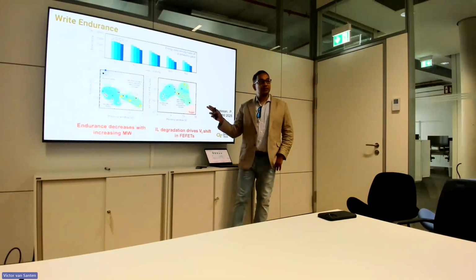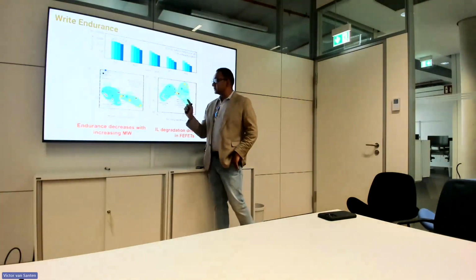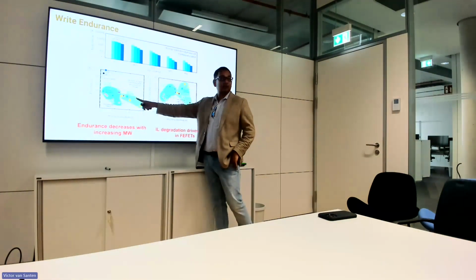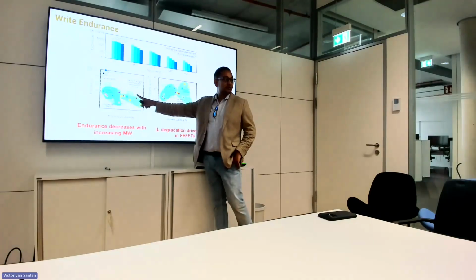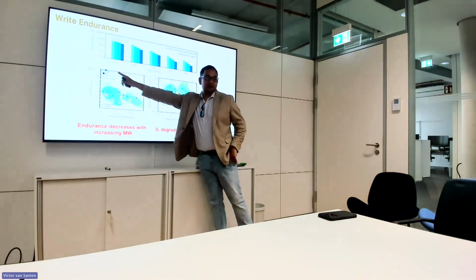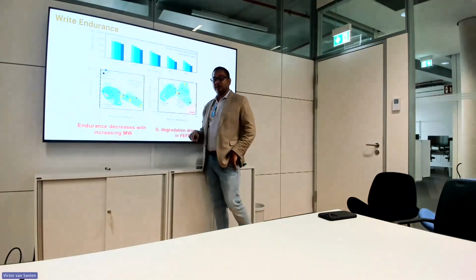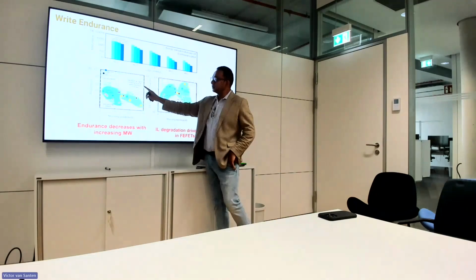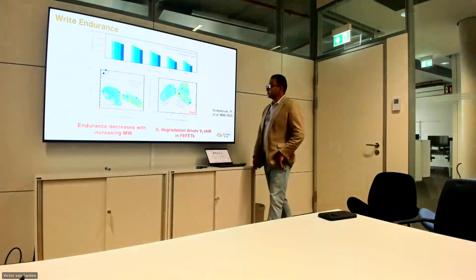But quite interesting that these data points are actually much closer to what we need for NAND technology than these data points, because for embedded you need much higher write endurance. But here you actually need to go up by only 1 or 2 orders of magnitude. Okay.